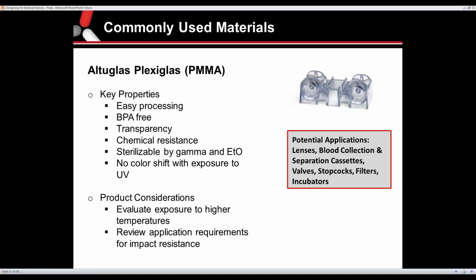Some considerations with the acrylic material would be exposure to higher temperatures. So this material, compared to, say, a polycarbonate that you can also get in clear, is going to have a little bit lower heat deflection temperature compared to the polycarbonate. So you just need to review the in-use temperatures to make sure that you're not exceeding the heat deflection temperature. Also, the impact resistance is not going to be as high as a polycarbonate. So if you have a component that is going to see impact resistance, you just need to evaluate this before going with the PMMA.